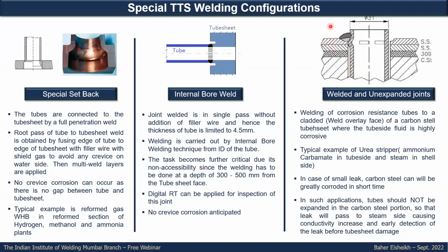Why? Because in the tube side here, the fluid is usually, as you can see in the carbamate service in urea plants, carbamate, which is highly aggressive to the carbon steel. So in case there is some issue in the tube to tube sheet joint, and some of the carbamate media will pass from here, in case you have a good expansion, you will have a restriction in the flow. This carbamate is highly aggressive to carbon steel, and you will see a case history at the end where you will see a very big cavity in the tube sheet because of that.